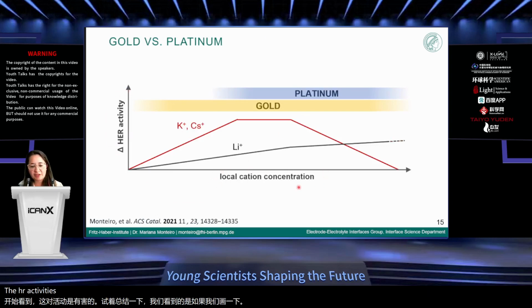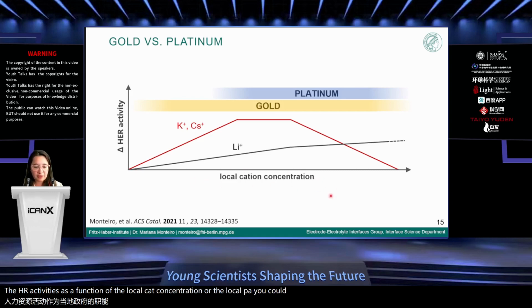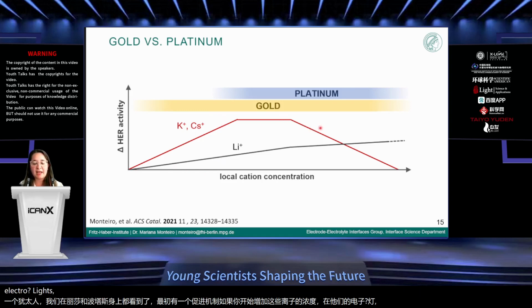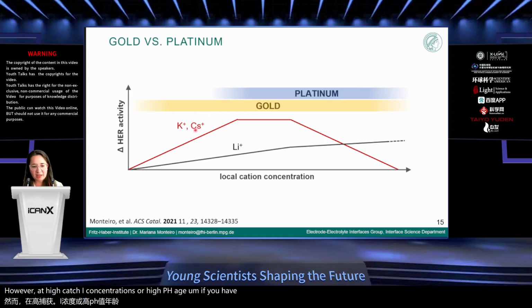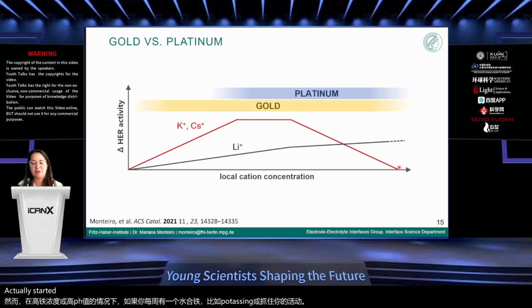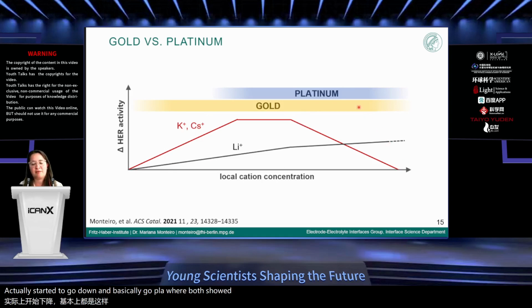So to try to summarize all that, if we plot the HER activity as a function of the local cation concentration or the local pH, you could call it one of the two, we see that for both lithium and potassium, there is initially a promotion regime if you start increasing the concentration of these ions in the electrolyte. However, at high cation concentrations or high pH, if you have a weakly hydrated ion like potassium or cesium, your activity actually starts to go down. And basically, gold and platinum both show this phenomenon.